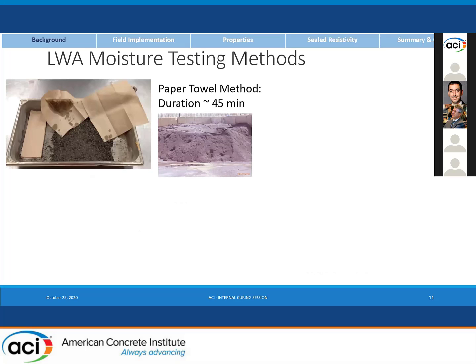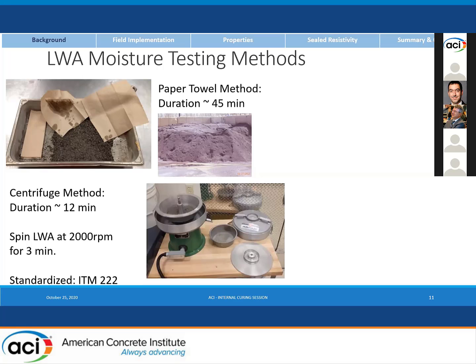So in the field, what we actually have is something like a pile of aggregates that's got a soaker hose on it. You may have been tempted in past years to go out there and try to run the only standard test at the time, which was the paper towel test in the field, and you'd be laughed off the job site if you tried to do that because it takes about 45 minutes and it is not a fun test. And so we actually implemented the centrifuge method, and it's now standardized in Indiana test method 222.